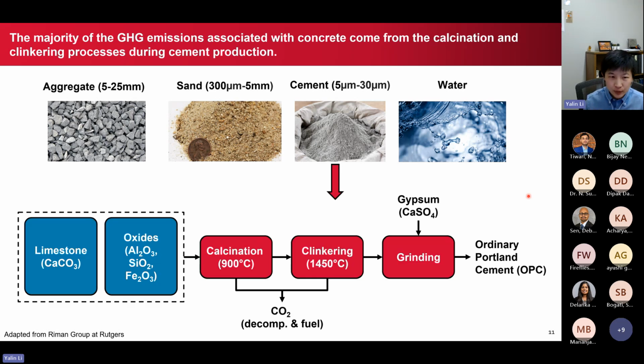And if we think about how we produce cement, we extract the raw material, including the limestones and other oxides, and then there's a calcination process. The main ingredient of limestone is essentially calcium carbonate, and during calcination it gives one-to-one molars of carbon dioxide. The temperature is very high, 900 degrees C at calcination, and the next step, the clinkering process, happens at 1450 degrees C, which is an even higher temperature. In both of these steps, in addition to the one-to-one emissions of carbon dioxide from decomposition, there's also the energy consideration. All of that adds up to the majority of the emissions associated with cement, and that's concrete. There are also some other steps you need to do to get what we call ordinary Portland cement, which is the most used type of cement, and people usually just call it OPC.